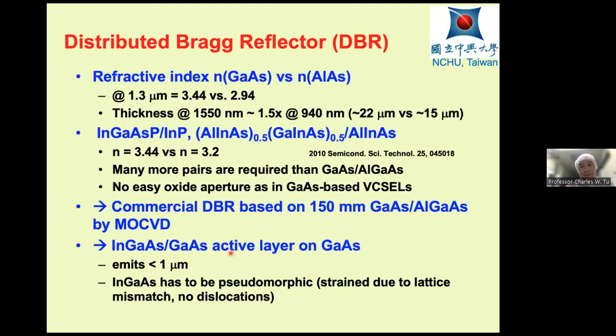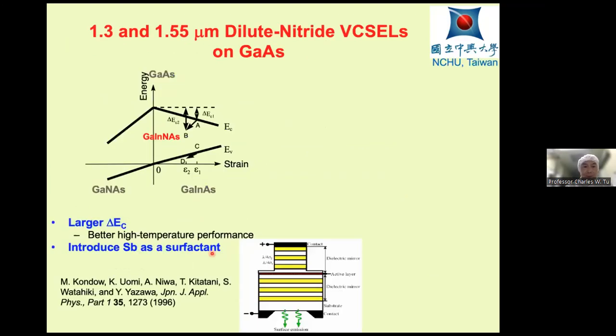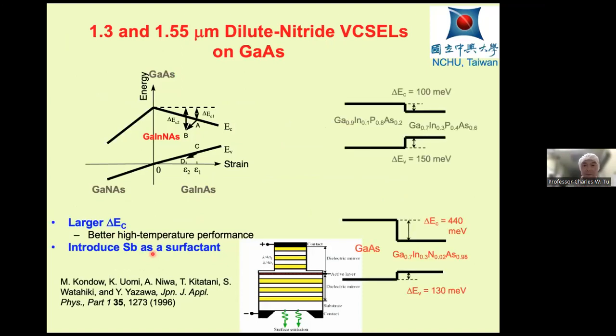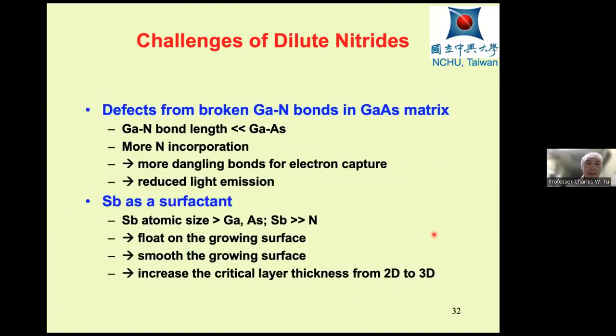And so this is where the dilute nitride comes in. Okay, the larger delta EC, and we introduce antimony as a surfactant, because antimony is much larger, so it tends to float on the surface, and flatten the surface. And again, here the larger delta EC.